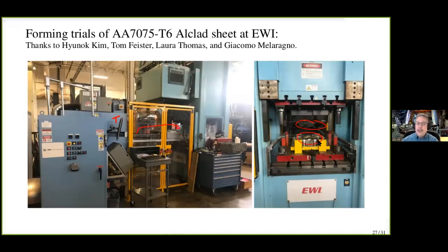Now, how do we figure out how much time at temperature, what temperature to use? Well, we actually used all the tools I just showed you. We were able to profile the temperature for its heating rate, use our thermally activated process ideas to predict how much time we're allowed to heat, how long we should hold at time, how much over temperature we should have, and then allow for the transfer time and cooling the part during transfer. So we're able to predict all of that because of the science we did before.